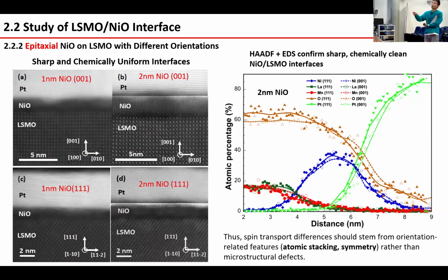Here we will compare the four figures. One is 1 nanometer on both orientations, and 2 nanometer on both orientations as well. This is to visualize the interface. We show that for the LSMO nickel oxide here, we can see a very clear sharp interface, and we also measured the EDS line profile. This is important for us.